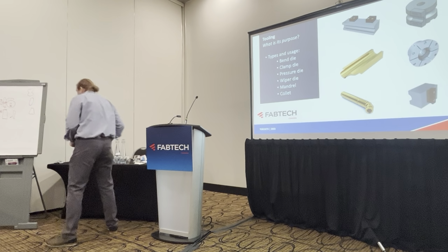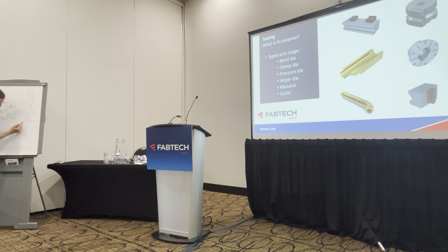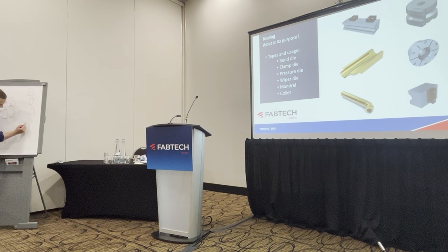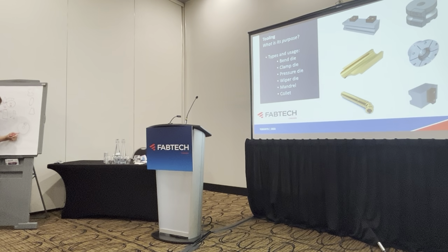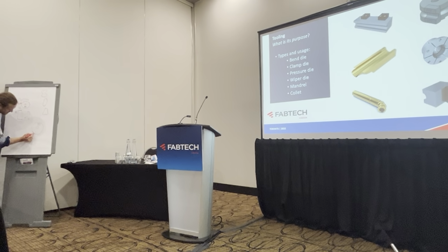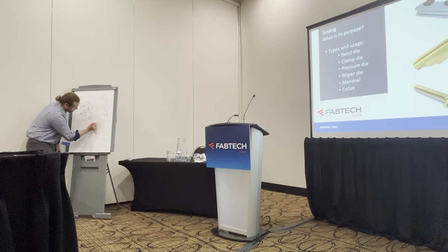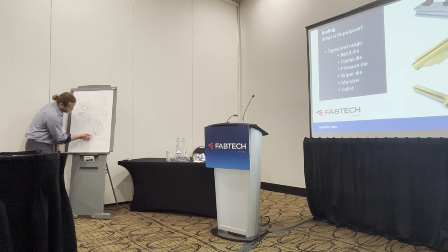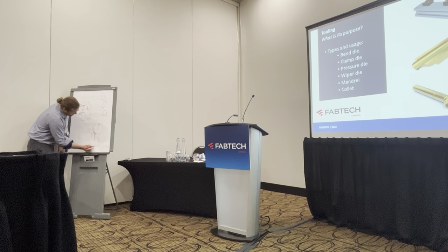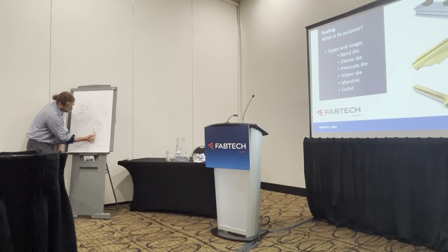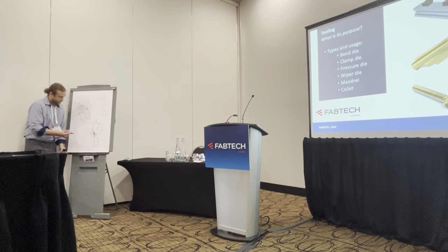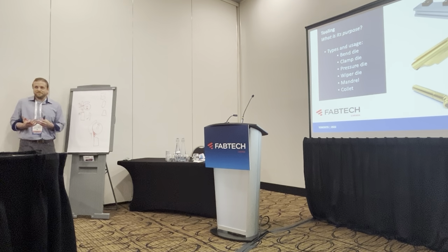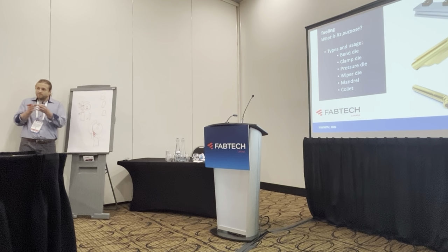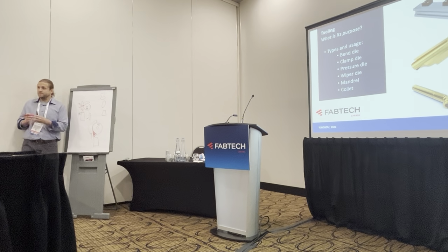And again, apologize for my drawing, but the principle behind it is you have a bend die right here, and there's a gap, I would like to say, right in here. And the tube's forming around here in this direction. So the wiper die, feathered in here, closes this gap. The reason I'm pointing this out is when you're actually forming steel, you can't physically see it turning. They like to call it plasticity, where it's forming and it's hot. If you take the tube out after forming it, it's going to be really hot.